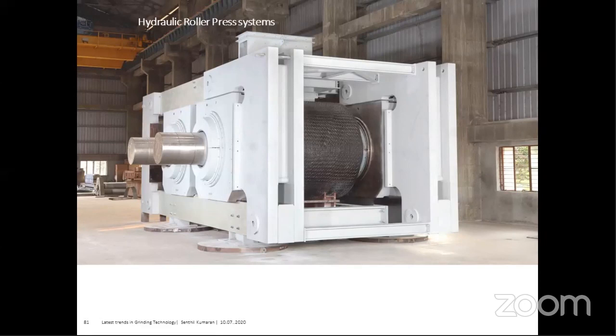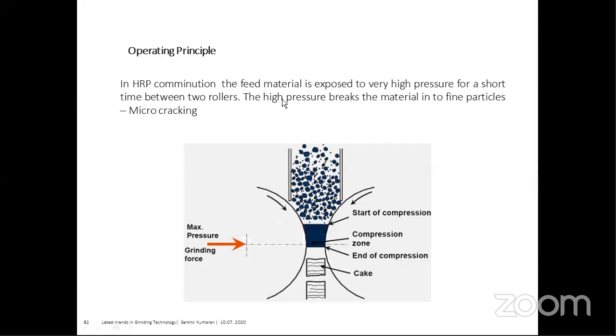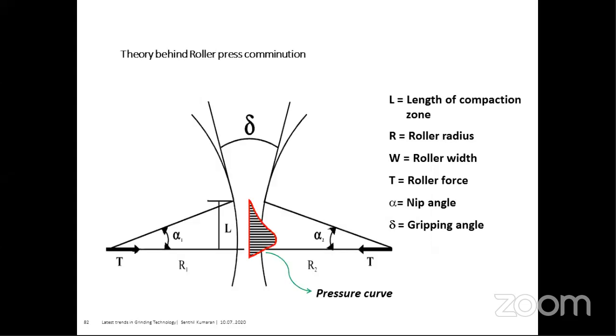Here we look at the third grinding system, the hydraulic roller press system. This is a view of a hydraulic roller press system. The operating principle is that comminution happens between two rollers rotating in different directions. The material is fed between them, and through the gap the material is compressed and forms a bed inside, and the roller press forms a cake. We won't get a fine product directly out of the roller press. The cake forms below, and it is later deagglomerated by deagglomerators installed in the system, and then it goes to the separator and is separated.